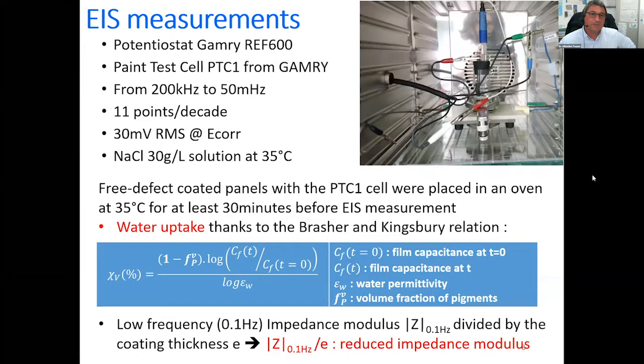So for EIS measurements, we use Gamry equipment. The frequency domain was between 200 kilohertz and 50 millihertz, with 11 points per decade, with an amplitude perturbation of 30 millivolts at the free corrosion potential. It is important to note that the free defect coated panels with the PTC1 cell were first placed in an oven at 35 degrees C for at least 30 minutes before EIS measurements, in order to be able to compare the panels that were aged in seawater with a different temperature than the panels that were aged in the lab at a temperature of 35 degrees C.